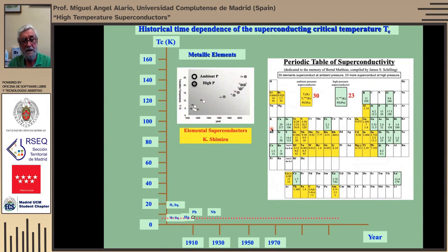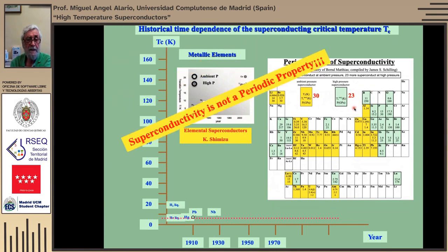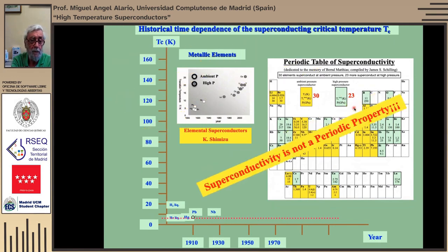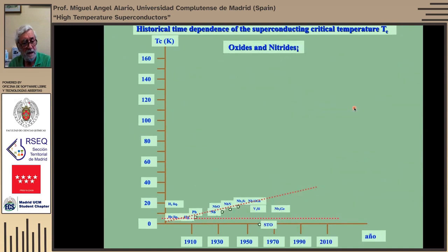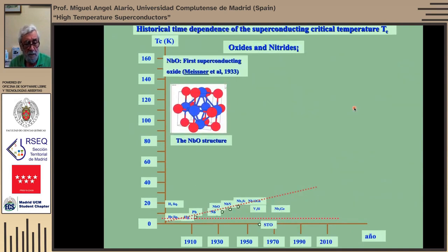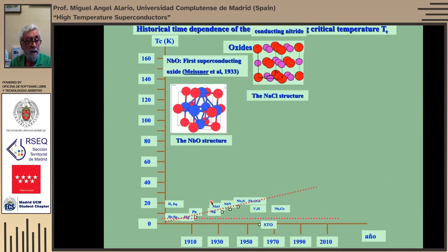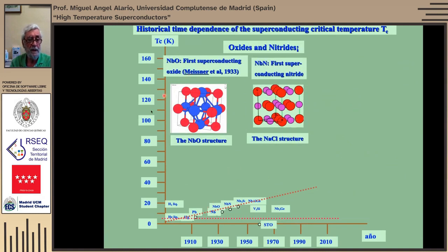In fact, we have 30 materials which are superconductors at room pressure, and 23 which are superconductors only under pressure. And in fact, it is not a periodic property, so it doesn't depend on the electron configuration, as all periodic properties do. But first the elements, then oxides and nitrides, the simplest one, NbO, and NbN, which has a sodium chloride structure.